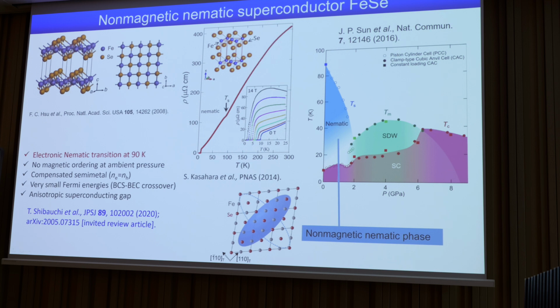So let me start with this 1-1 system. I think all of you know this material, and it has a very simple crystal structure of just layers of iron selenium like this. The most important point of this material is that it has a so-called electronic nematic transition at 90 Kelvin, but it doesn't show any magnetic order down to 0 temperature, which is different from the 1-2 system. So this material is very important for studying the interplay between nematicity and superconductivity. You can find superconductivity at 9 Kelvin without any doping.